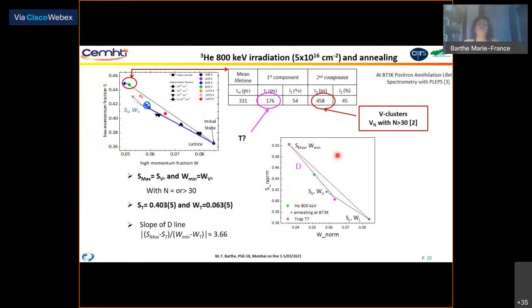And I will come back to this question, what is the S-max W min? If you remember, I showed you some annealing for the helium irradiated sample, we found at the temperature of 873 K two lifetimes, with one corresponding to vacancy clusters, and the second one at 180, not too far. And the question is, what is this lifetime? To which type of defect does it correspond? We can say that this point, corresponding to these annealing conditions, is on a line between 2 points, the S-max W min, and this star that could be this lifetime.